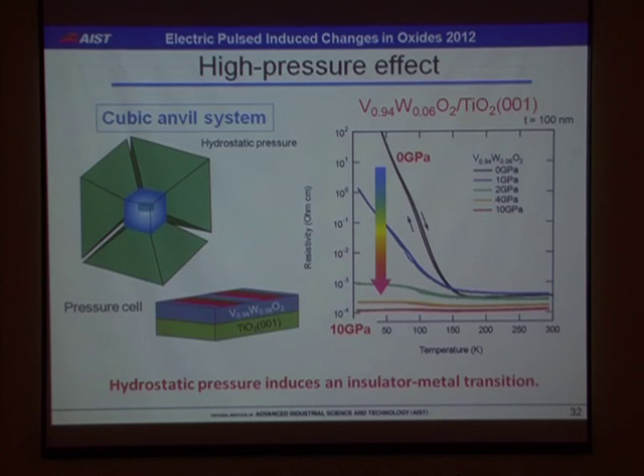So this is our pressure effect for this electron-doped VO2. Originally, again, this insulating ground state was suppressed, and the resistivity is suppressed by applying pressure. And here, we utilize a cubic anvil system in order to apply hydrostatic pressure. And we measure our sample in this system. And by applying more than 4 gigapascal, we observe the metallic ground state.